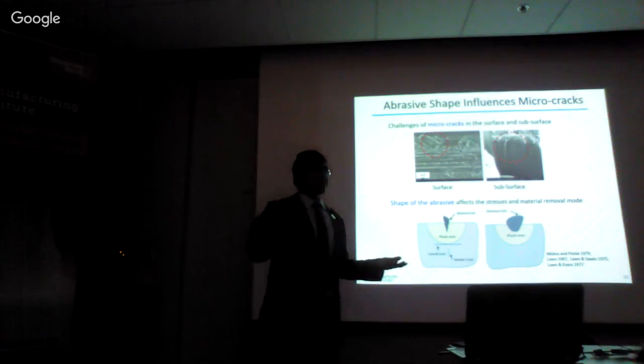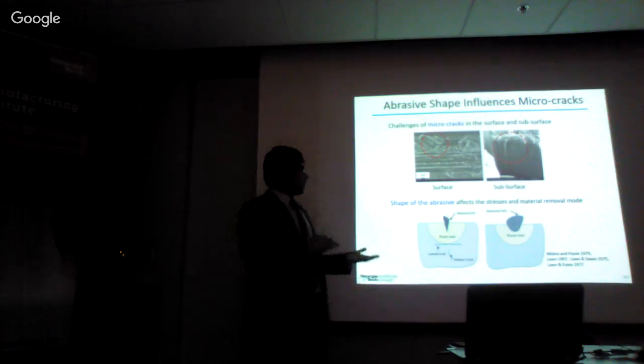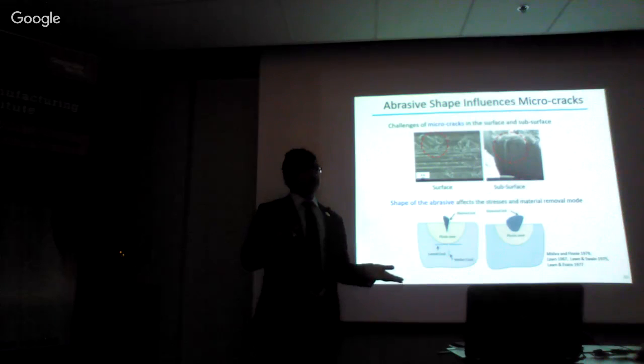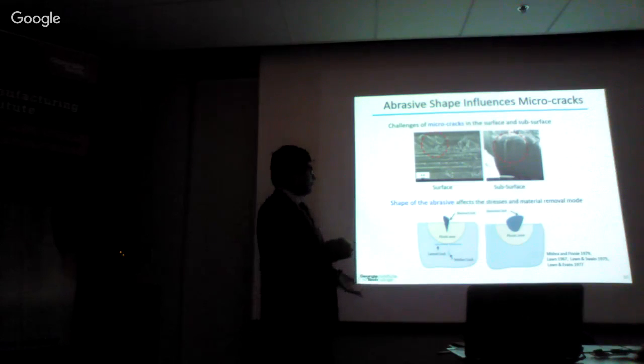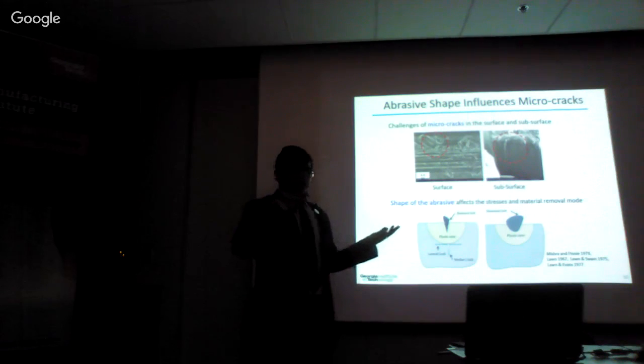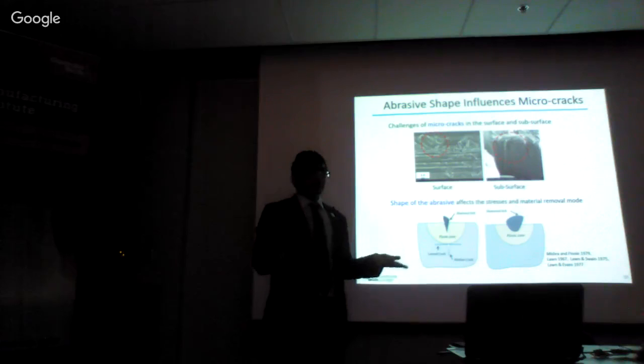Whereas if we have a rounder shaped abrasive or indenter, like a spherical indenter, it will not create as many cracks, it will only create a plastic zone. So the shape of the indenter critically affects the stresses and hence the material removal mode, whether it is ductile or brittle, with cracks formed in the indentation and scribing process. But in this PhD thesis, I'm looking at the effect of actual abrasive grit shapes, which are not as idealized as indenters. So let's look into that.